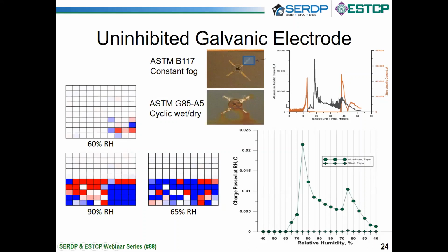So this is some of the raw data from those. On this axis, you see time. This is time, but what we did was scan the relative humidity, and I apologize, I don't have it in relative humidity scale. And you can see the cumulative current. So for all the red squares, we added up the currents of those. And so you can see, and this point corresponded to about 60% relative humidity, you get corrosion occurring on the steel. And as you approach deliquescence, the aluminum electrodes start to corrode as the film forms and the steel shuts off. So this is only anodic current, again, because it becomes cathodic.